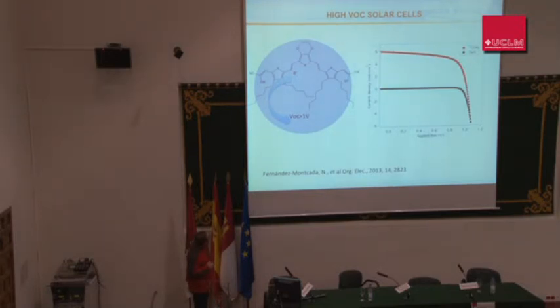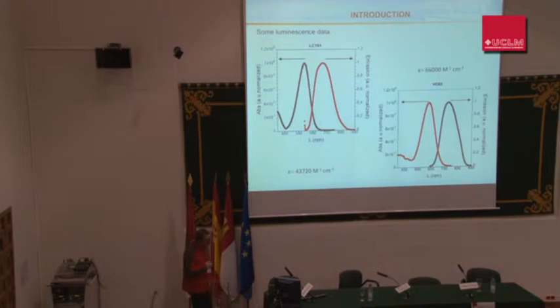The importance of fluorescence is that you can check, when you mix this with an electron acceptor, usually a fullerene derivative, whether all the excitons you form are split into polarons, or whether the excitons stay there and come back to the ground state, and then your solar cell is not very efficient. If you don't have luminescence, then everything becomes much more difficult to quantify.